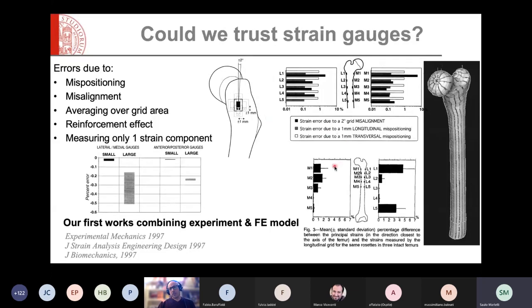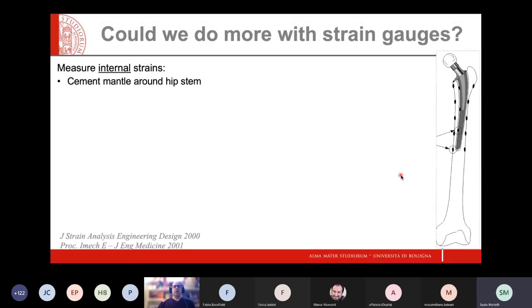We also wanted to see the effect of using a uniaxial gauge, which was cheaper and easier to use in measuring strain, as opposed to measuring all the components of a strain using a 3-axis strain gauge. And we observed quite large errors. So from then on, we actually used only 3-axis strain gauges.